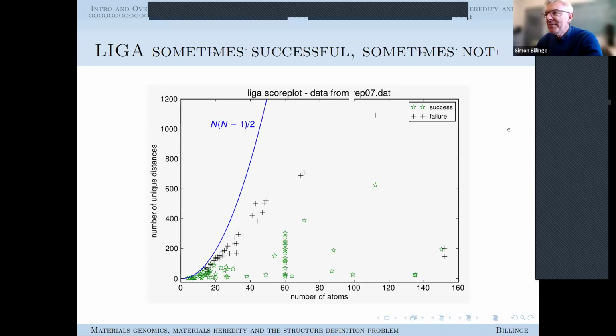And what we found was that sometimes LIGA succeeded and sometimes it failed. So these stars were the ones it succeeded on, and the crosses are the ones it failed on. And you might think that, oh, it's going to fail on the big ones and it's going to succeed on the small ones. But what we found was that actually it could succeed on really big ones. And sometimes it would fail on very small ones. So the size of the cluster was not the issue.